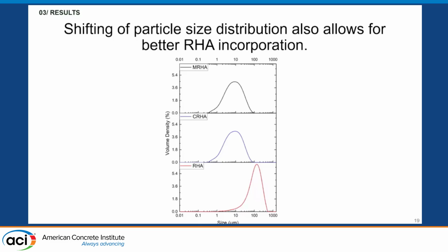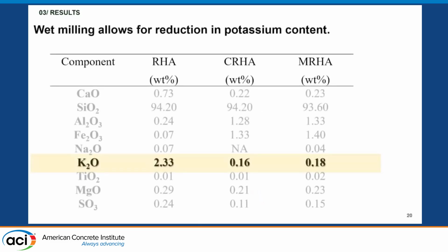cement mix. But another big thing is by doing wet milling as opposed to dry milling, you're also able to do a leaching process. And so something that is amazing for plants is potassium. They need potassium to grow. But the big issue is we don't want a lot of potassium in our cement. We don't want potassium-rich cement. That's not great. So by doing this wet milling process, you actually have a pretty substantial decrease in the potassium